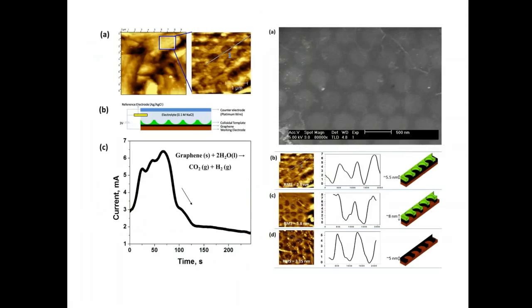Indeed, we were successful in patterning graphene oxide using this colloidal templating method. Here is an AFM image which shows the modified graphene oxide and the holes where we used to have the colloidal template.